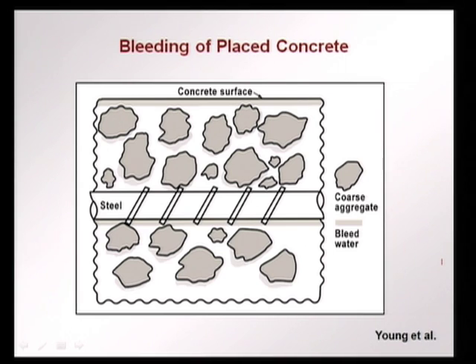That is what is shown here in this picture. You have the laitance here at the top surface, the bleed water goes up, rises to the top and forms this weak surface at the top. So, this weak surface will obviously not have much abrasion resistance and will be of poorer quality than the rest of the concrete. More importantly, we find that there could be an accumulation of bleed water along the bottom of the coarse aggregate or below the reinforcement bars.